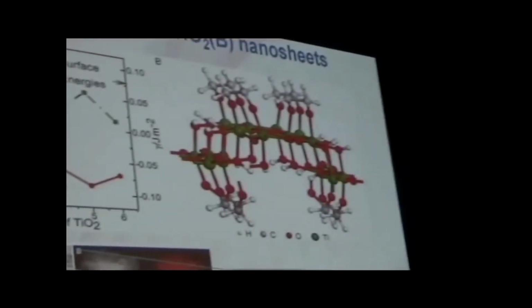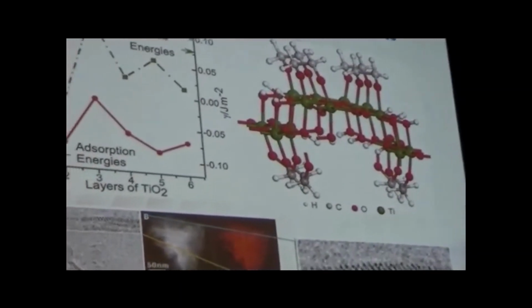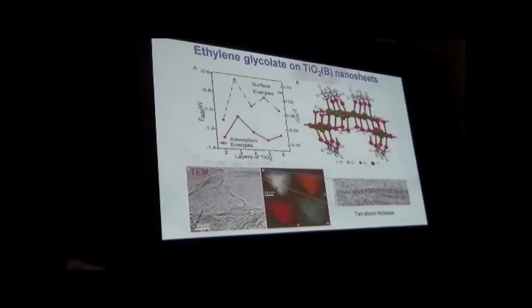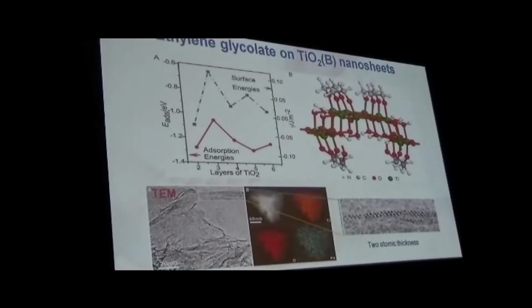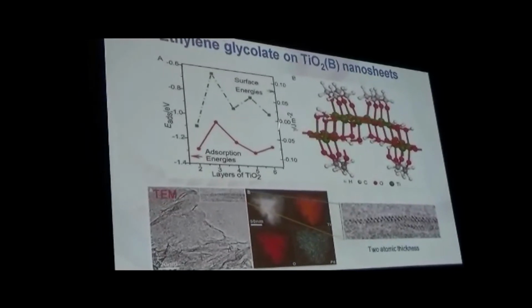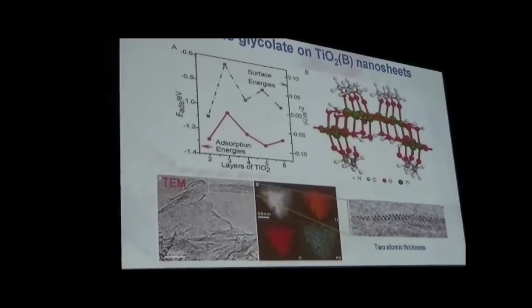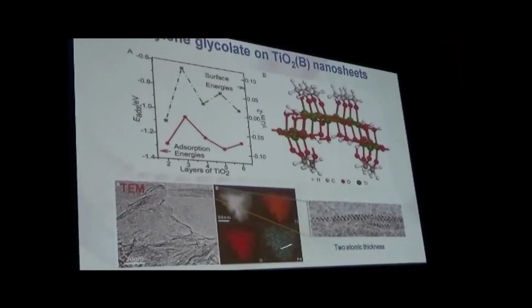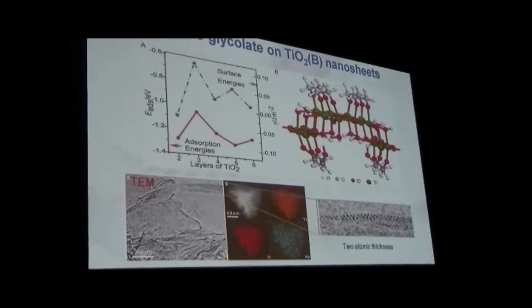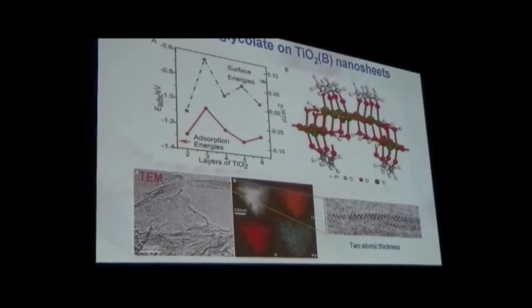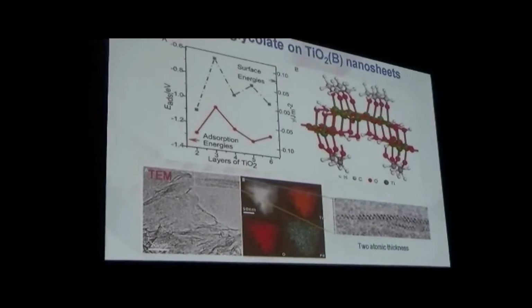By means of DFT calculation, we can estimate the surface energy. To prepare the TiO2(B), we use the method proposed by Wang Xun from Tsinghua University. To prepare the titanium ultra-thin nanosheet, we add some ethylene glycol on the surface. In this case, in the surface energy calculation, two layers is the most stable. Accordingly, in the experiment you can observe here, it is two atomic layers thick, with a very large surface area.